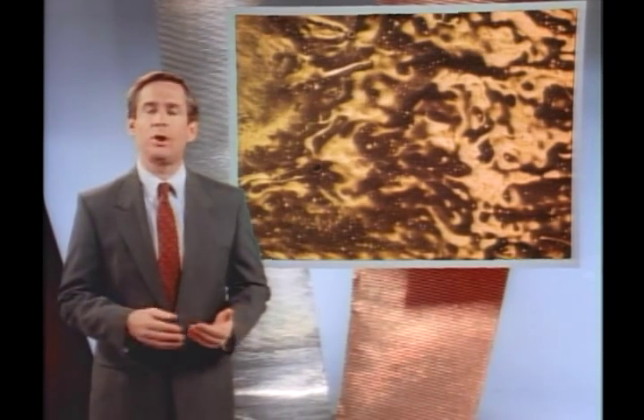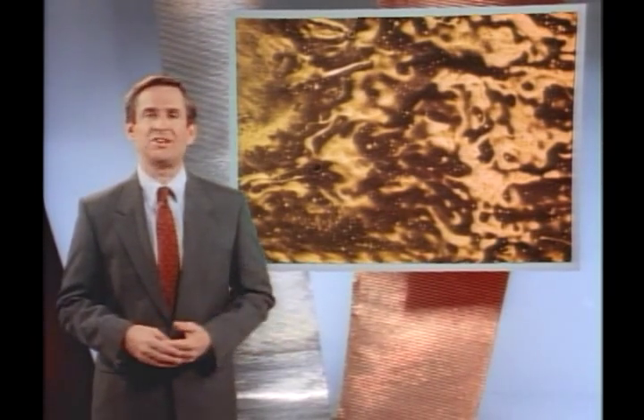Now, compare that to this sample of a competitor's blend, which under the microscope shows black regions, a telltale sign of a poor blend. It's important to realize that even the microscope doesn't tell the whole story. It's possible to achieve phase inversion with raw materials which, when blended, will not expand and recover as well on the roof. For instance, two asphalts with exactly the same physical properties could have totally different blending characteristics with the polymer. And that's why Siplast stays with its proven source of asphalt and the same polymer. When raw materials vary, as they do in this competing product, adjustments or compensations must be made to it. And each change requires more changes, which could lead to poor long-term compatibility. The result can be premature phase separation of the asphalt and polymer, resulting in roof failure.